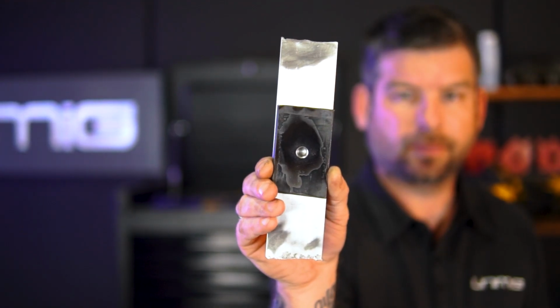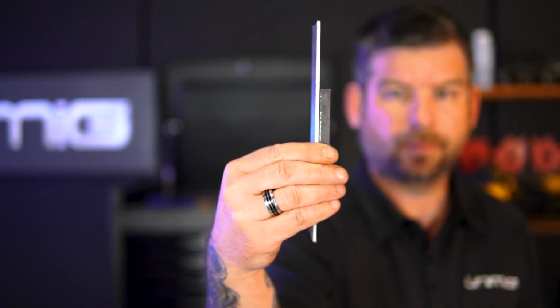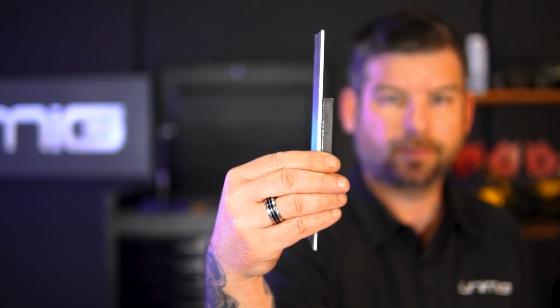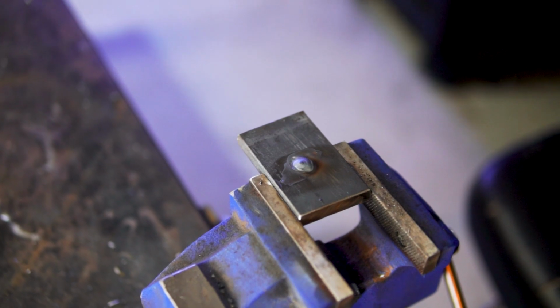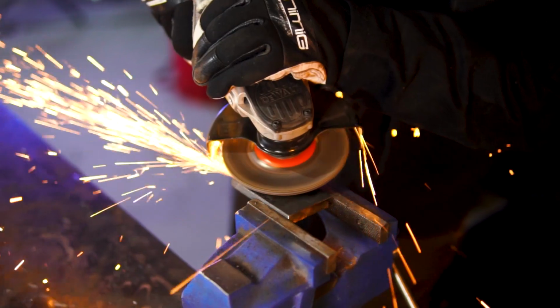The reason I weld around the edges is so that I can bridge the gap and it doesn't drip through. Also, in some circumstances, you can use an aluminium, brass or copper backing plate to assist you. But in this demonstration, I won't be doing that because you can get perfect results using the before mentioned technique on both sides and then sanding it back.